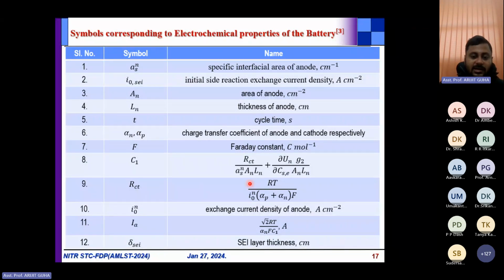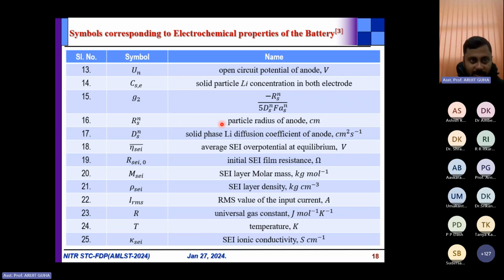Okay, and there are certain other parameters, like this charge transfer resistance, which depends on the universal gas constant, temperature, and all this interdependency is there. Okay, you can see here. And as the SEI layer thickness in the battery is growing, in order to quantify that, we have used this quantity called delta SEI. Delta SEI denotes the SEI layer thickness. Okay, because only as the thickness increases will the resistance increase. Okay, so there are other sets of parameters which are involved in the battery.